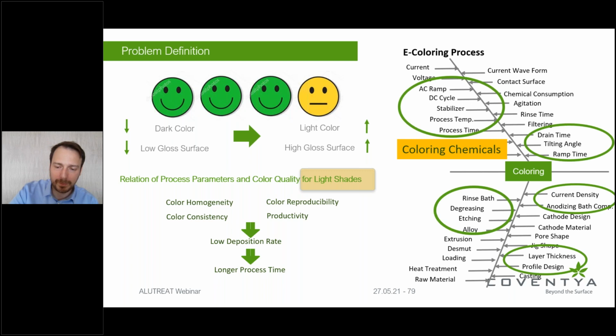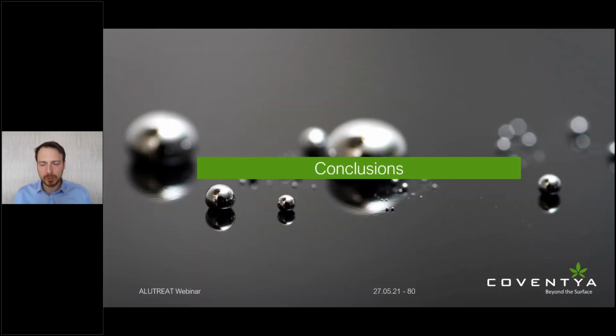So, as conclusions, we know that anodizing, or the performance or the shade or the color of the surface, is influenced by manufacturing. And not only that, it's very complex because, as we have seen, if something changes with the pre-treatment, the color of the profile could change completely. Or if the anodic cycle is not done correctly, or if you're speeding up too much, even with black, you can have problems. Therefore, you need to get these two perfectly in line so that you have a chance in coloring to match the color or get the desired color.